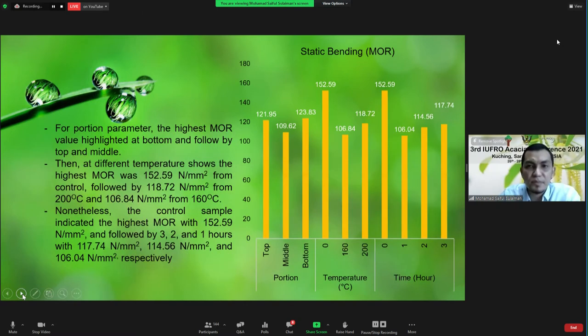Okay, so this is the MOR value for the static bending. The slide shows the MOR value was highest at the bottom portion, followed by the top and middle portions. The maximum fiber stress of the acacia hybrid was determined to decrease proportionally as the thermal treatment was applied to the sample, and the comparison between values is indicated in the figures respectively.